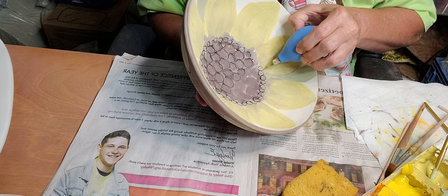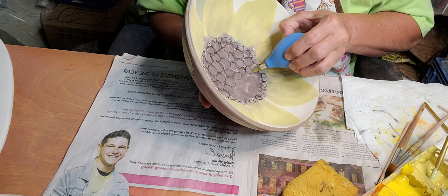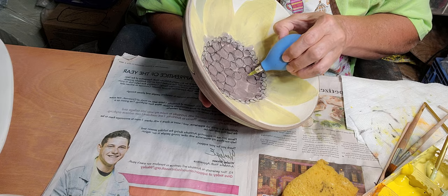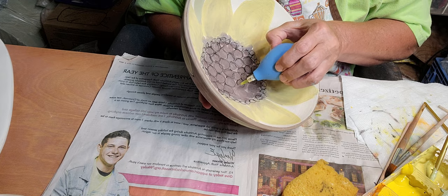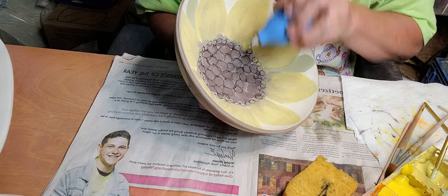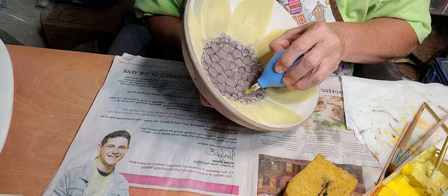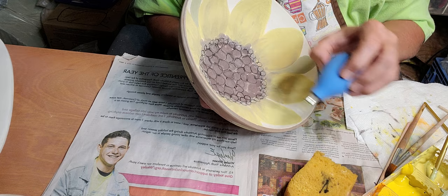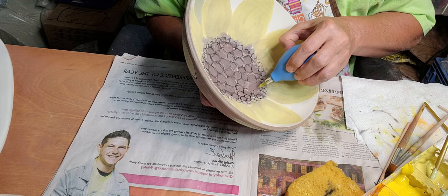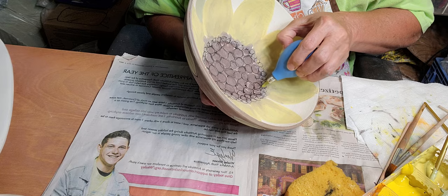Colors are definitely richer if you're doing it low fire - they stay much brighter. But as long as you don't water them down, underglazes can be used from low fire like cone 018 all the way up to cone 10, because underglazes are really just clay and pigment - clay and stain. They don't have any flux in them, which is the glossy part.